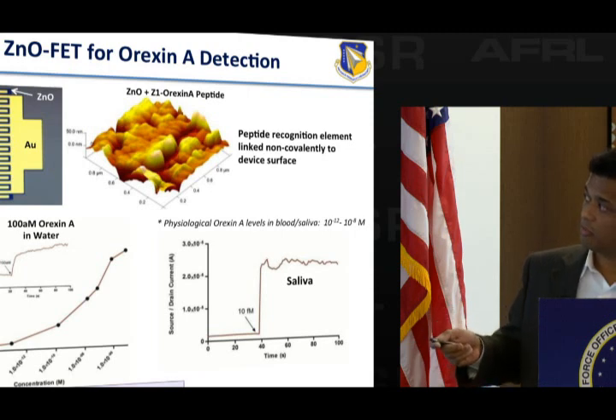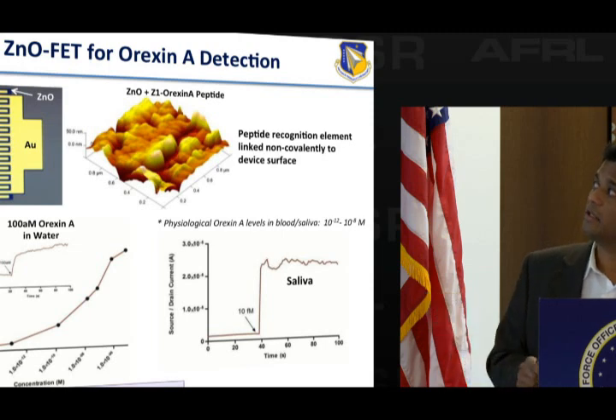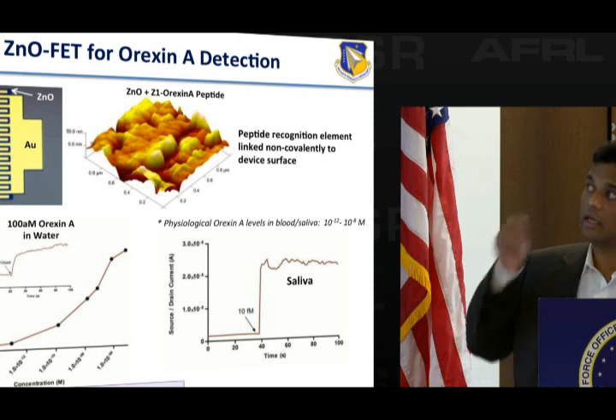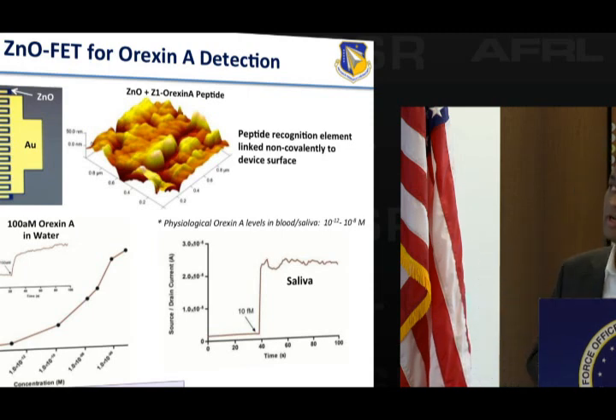And this is just a computational modeling showing the binding peptide and the target. And we put a zinc oxide-binding peptide on the other end, coated a zinc oxide FET device that was provided to us by the Sensors Directorate. This is just an AFM image showing that a peptide likes to bind to the zinc oxide specifically and not anywhere else. And we see 10 orders of magnitude response in the device in the presence of this peptide.